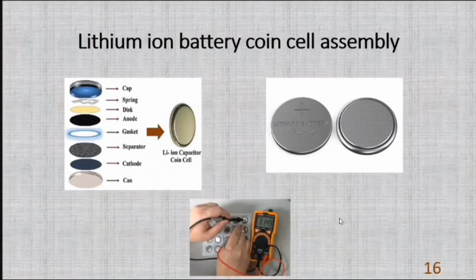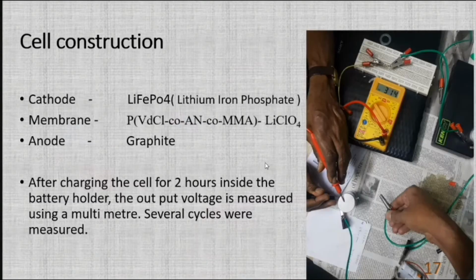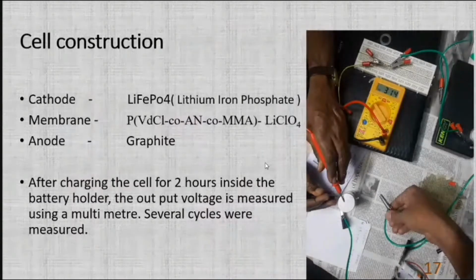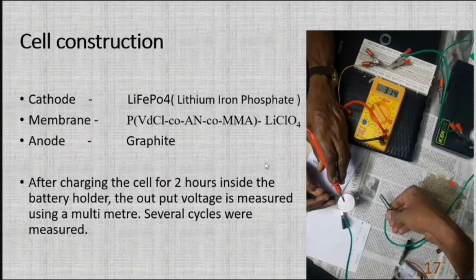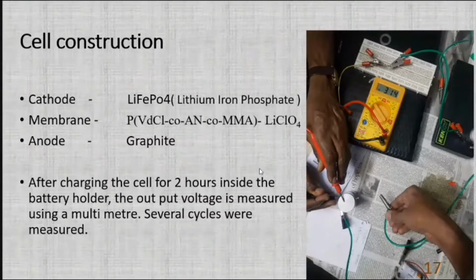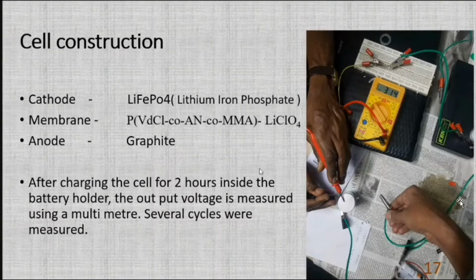Here we have taken the coin cell crimping machine to fabricate our battery. Our batteries consist of a lithium iron phosphate cathode, which is well known around the world and used in commercial batteries. It is coated over an aluminum current collector, and the membrane with the highest conductivity is taken as the separator as well as the electrolyte. No liquid electrolytes are used. The graphite is used as the anode, which is coated on the copper current collector. The battery is mounted on a battery holder and charged for 2 hours.